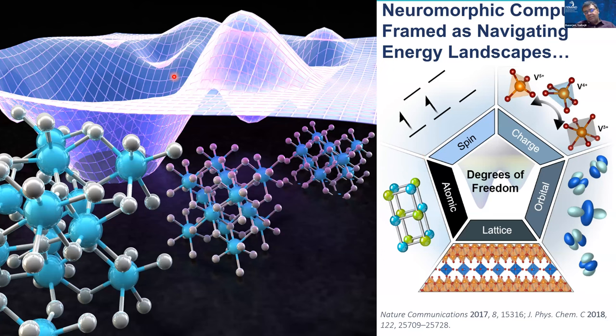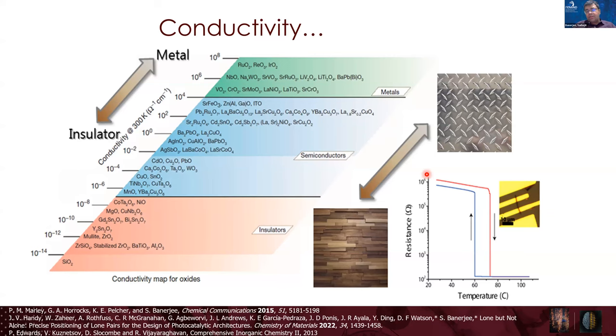So coming down to materials, we can frame this as a problem of navigating energy landscapes. How do I go back and forth across multiple local minima and through large barriers or small barriers? How do we modify barriers and change coupling of spin, charge, orbital, that is atomic degrees of freedom? So we'll start with a compound that has gotten a lot of interest for many decades, which is VO2, which has this large electronic transition.